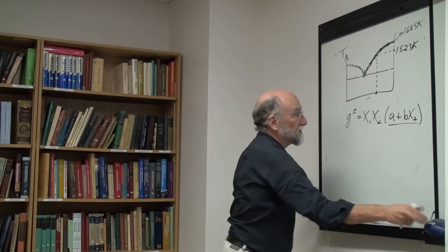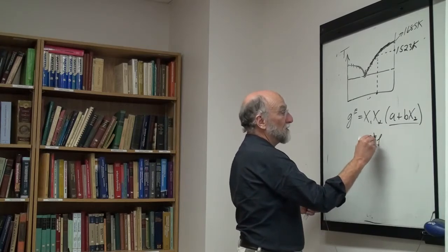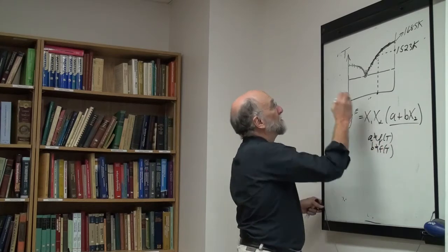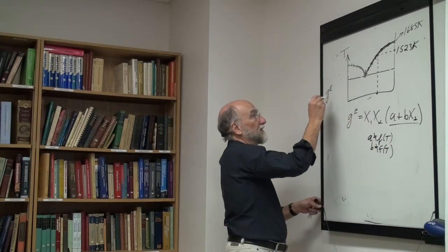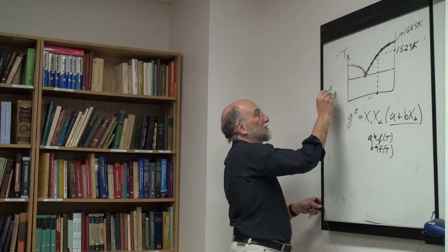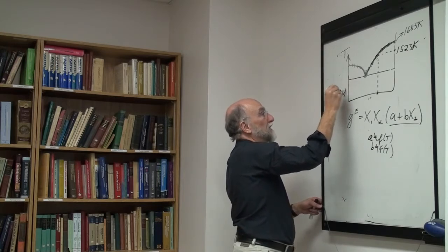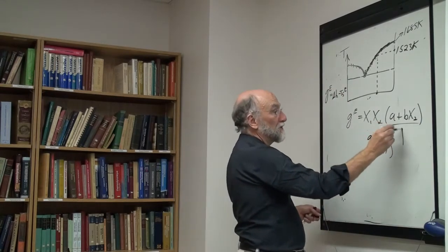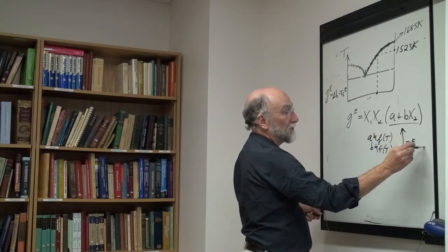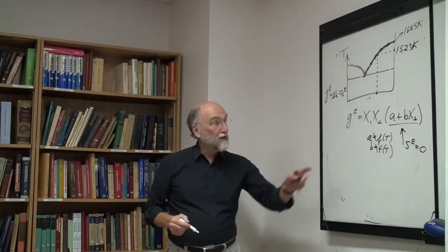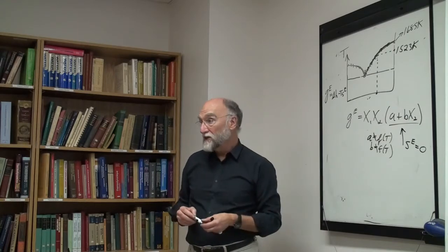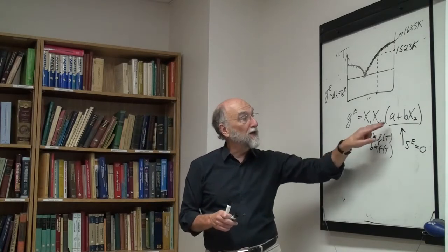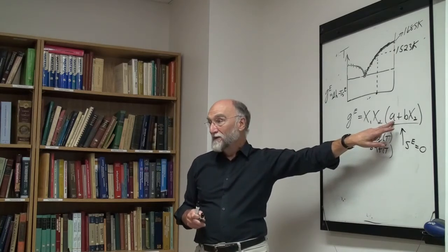What that means is that a does not equal a function of T, b does not equal a function of T. Remember that GXS is equal to delta H minus T SXS. So by not making this a function of T, what I'm really assuming here is that SXS equals 0. And I'm putting the extra term into the delta H term. Remember, the strictly regular solution with x1, x2 omega, that's all enthalpy.